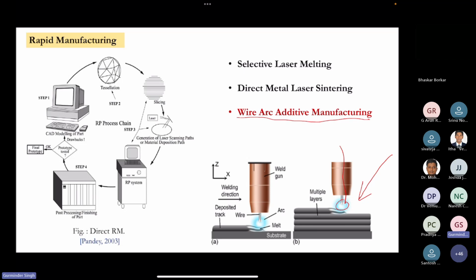It has a limitation. Similarly, it has trouble with high melting point materials, and also copper, high thermal conductive materials, and reflective materials, and the surface finish of these parts is not good. You always have to do some post processing to remove the cutting edges to get a flat surface or a high surface finish product.